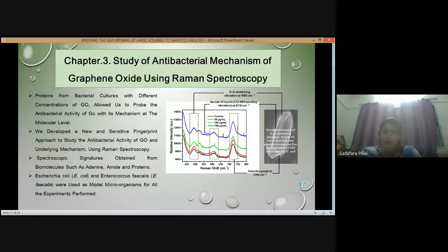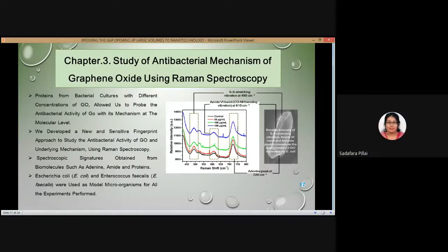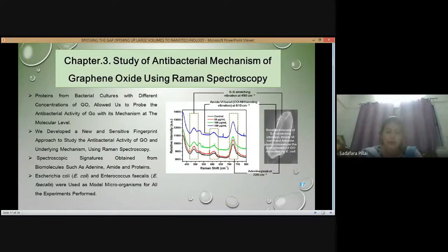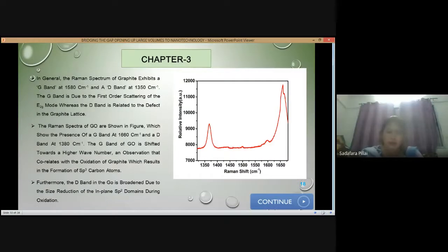And this is another study, the antibacterial activity. Like currently for coronavirus, we need what? Antiviral activity. So this is one study I did, antibacterial activity by using graphene oxide and Raman spectroscopy. Graphene oxide has sulfur stretching, amide 6 band, nitrogen hydrogen bonding stretching, and disulfide bond. So when you put the graphene oxide with the bacteria, its concentration increases: 50 microgram per ml, 100 microgram per ml, 150 microgram per ml. Then you can see the Raman band.